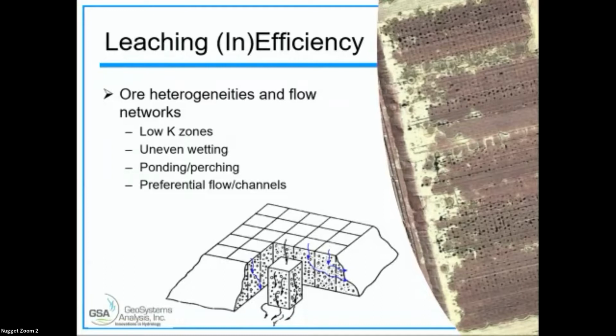And we talk about leach efficiency. What we're really focused on is inefficiency. And this is because you have heterogeneities with the ore, even with a crushed ore sample and agglomerated, and you develop flow networks. You can have low K, by K I mean saturated hydraulic conductivity, uneven wetting. You can get ponding and perching not only at the surface, but at the bottom, and preferential flow and channeling. So if you start having preferential flow and channeling, then that really reduces the efficiency of your operation because you don't have a nice even distribution of solution, and it's going to affect your recovery.